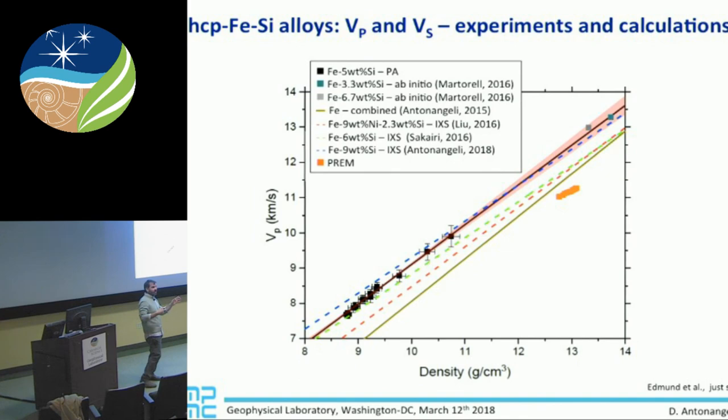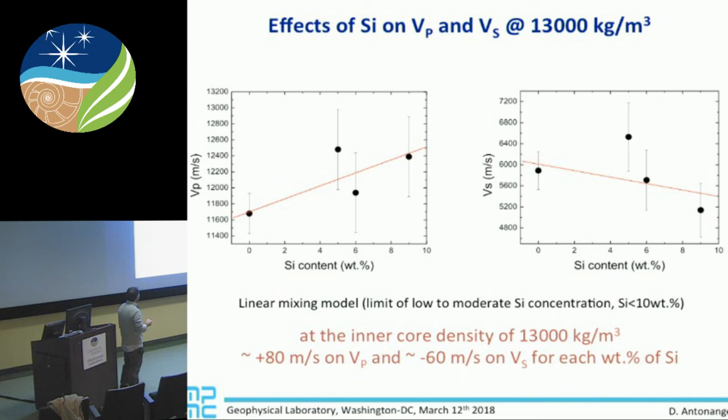So definitely some more work is needed, but we can qualitatively understand this based on the geometry. Picosecond acoustics measures velocity along the compression axis of the cell, while inelastic X-ray scattering measures the velocity perpendicular to the compression axis. So especially at the highest compression, where we start developing some texture, with typically the C-axis aligning along the compression axis, we might start probing slightly different preferential orientations. So where we are probing more the C-axis, we are probably faster than where we're probing more the basal plane.